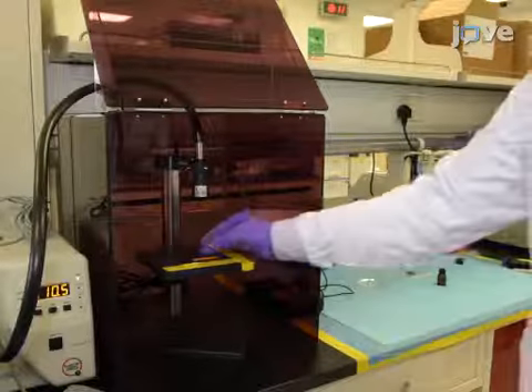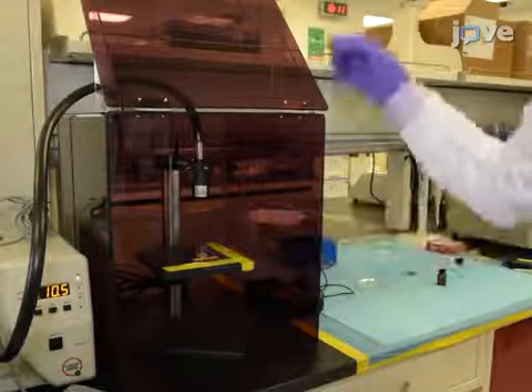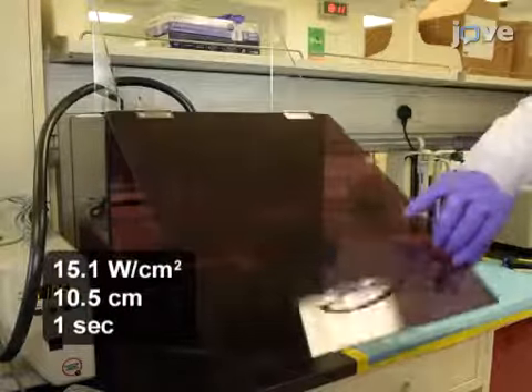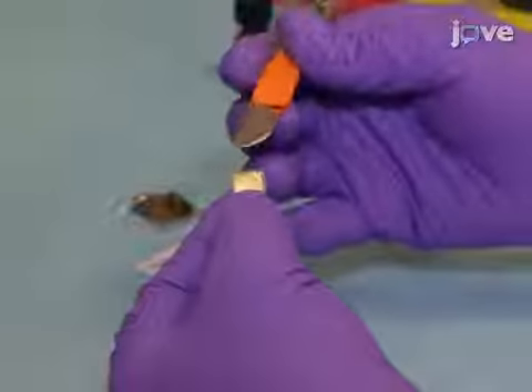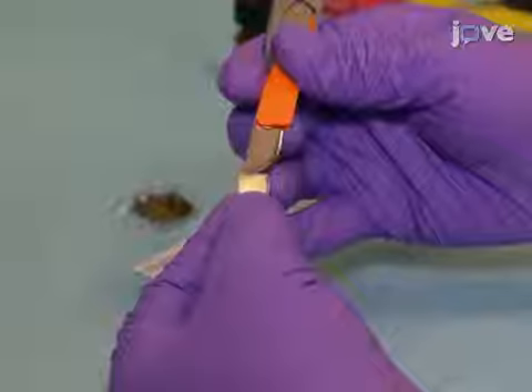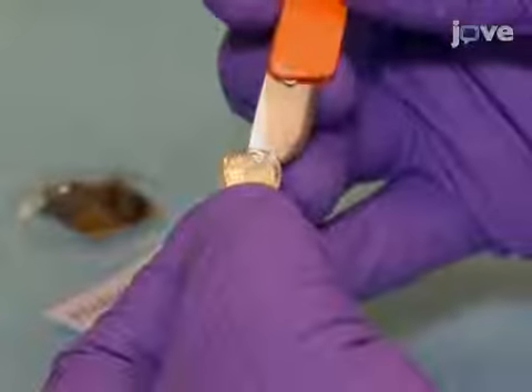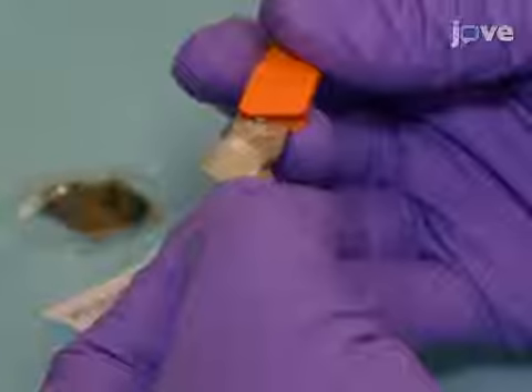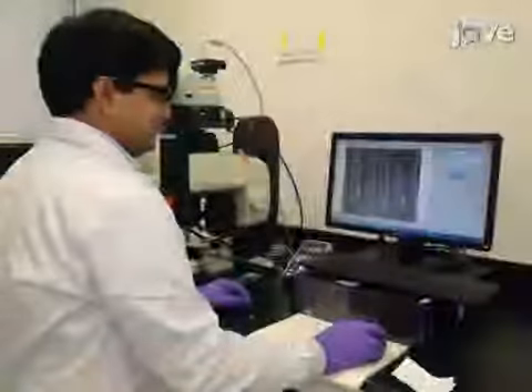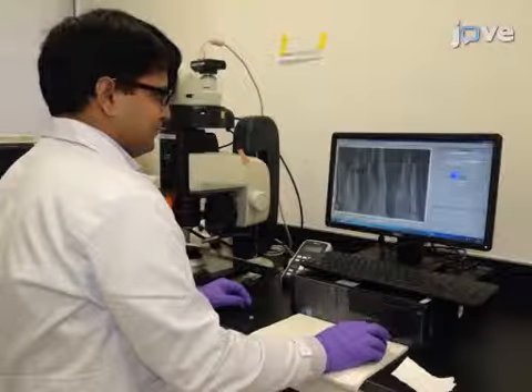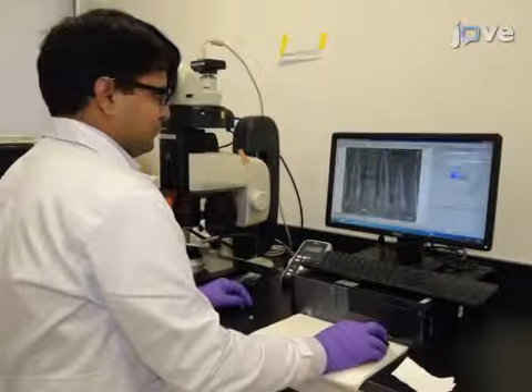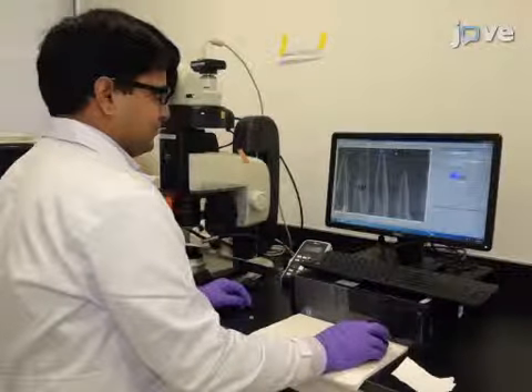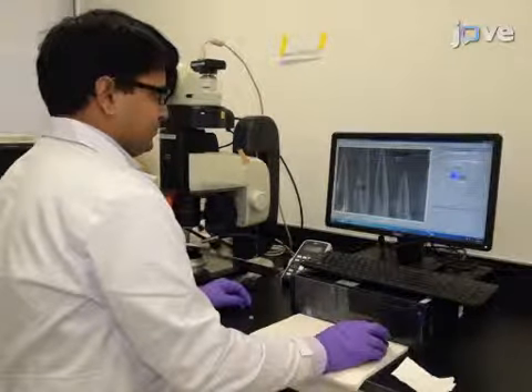Next, irradiate the setup with high-intensity UV light measuring 15.1 watts per square centimeter from 10.5 centimeters away for a duration of 1 second. Once the backing layer has polymerized, separate the backing layer on the microneedle array from the photomask using a sharp blade. Then, quantify the length, tip diameter, and base diameter of the microneedles with the backing layer using a stereo microscope.